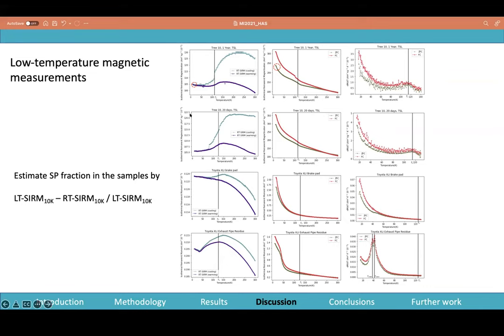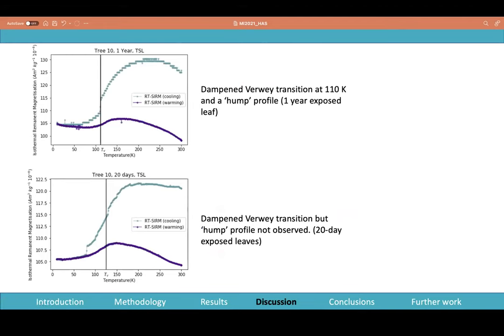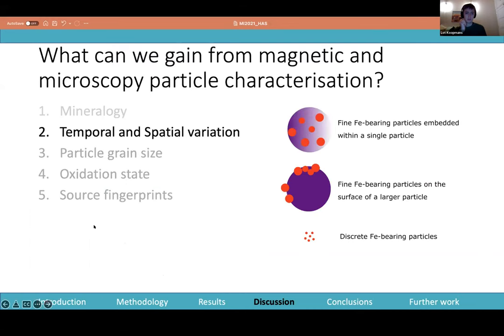You can also estimate the SP fraction by measuring the room temperature SIRM over there and subtracting this value from this zero field low temperature SIRM, which is where you get this higher fraction, because these SP particles, which are unblocked at room temperature, get blocked at these lower temperatures and act more single domain like. This is something which I've already discussed, the hump profile and the dampened.